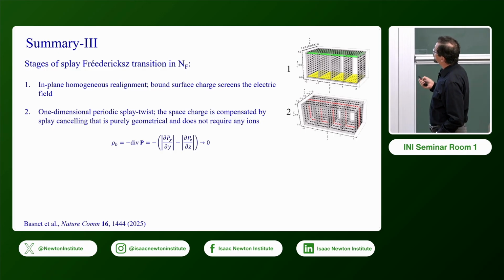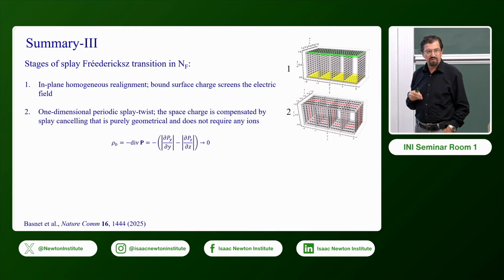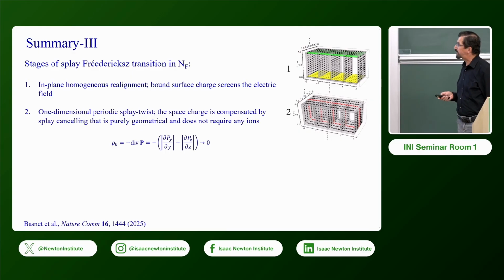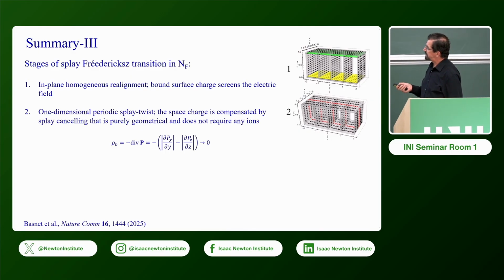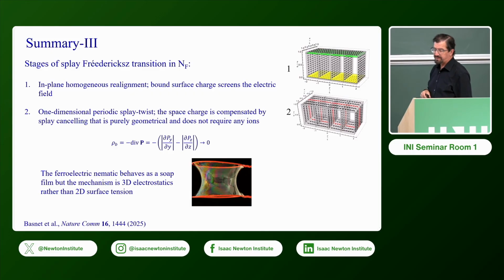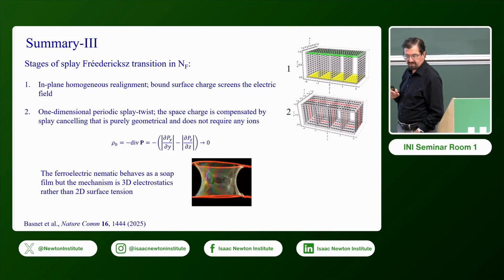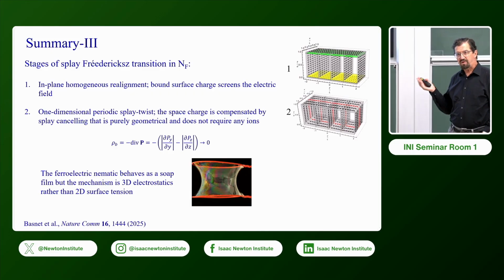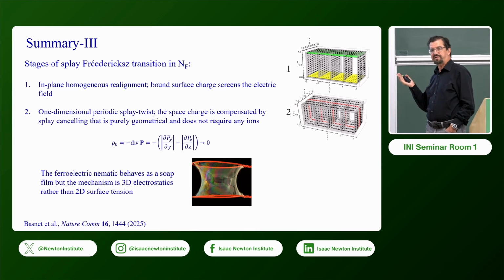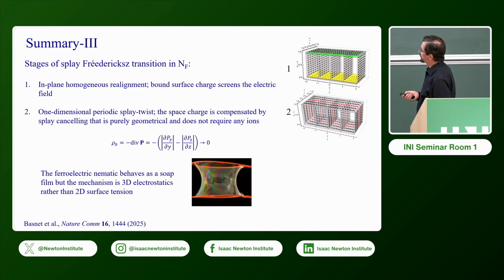So the conclusion for this part is that there is a nice geometrical approach to solve the electrostatic problem associated with the space charge simply by introducing the secondary splay in the orthogonal plane. So the problem is reminiscent of the minimal surfaces problem, the Plateau problem, but the underlying physics is not the minimal surface, two-dimensional surface tension, but rather three-dimensional electrostatics. But in another sense, the mathematics might be similar.